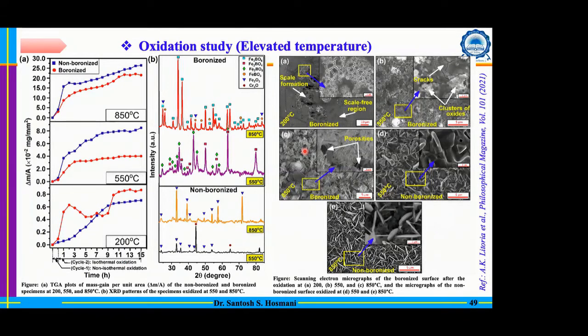However, at 200 degrees Celsius, you can see some erratic behavior. This erratic behavior is linked with the porosities which are formed at the surface. That means we need to address the bad quality surface, which especially happens in the case of boronizing. So that is a challenge, especially for the lower temperatures.